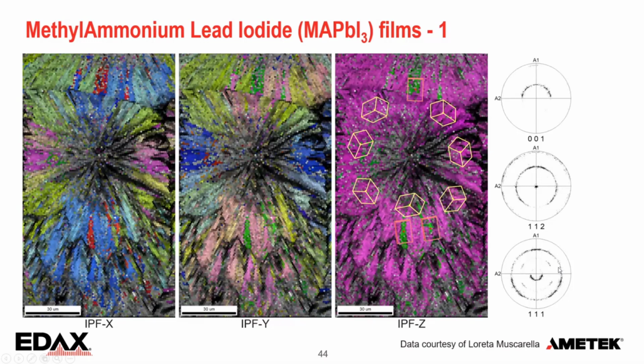But if we look in plane, the one we just had was the IPFZ, so it's sticking out of the sample. When you look in plane, we have a symmetric orientation distribution. So top, bottom, and left, right are clearly different. They are mirrored almost. And here in the pole figure, you can see how the whole thing is oriented.